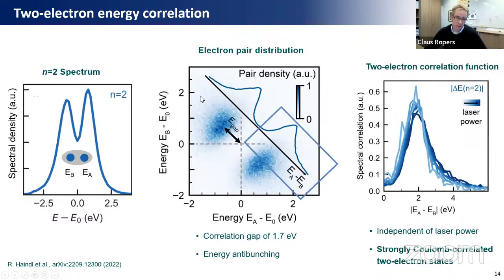If we just plot this now as a function of the difference energy, this is the energy correlation function for different laser powers. It's only weakly dependent on laser power. And this shows that there's actually an energy correlation gap of more than 1 electron volt, which means that it's not possible to emit 2 electrons from this source with an energy within the laser pulse duration, about 150 femtoseconds.